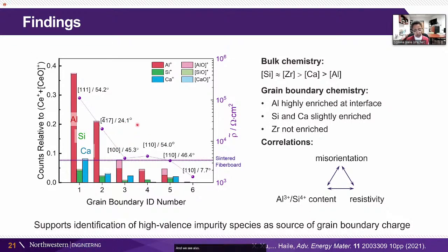And we see also somewhat of a correlation with the nature of the crystallographic relationship between the two grains. When the two grains have a smaller angle misalignment, we have a lower impurity concentration and a lower overall impedance. And from a thermodynamic perspective, it makes sense that if you have an interface which has a low surface energy because it is a nicely aligned interface, then there's less of a thermodynamic driving force for the impurities to be trapped there. And so that gives you a low impurity concentration and therefore a low impedance across that interface.